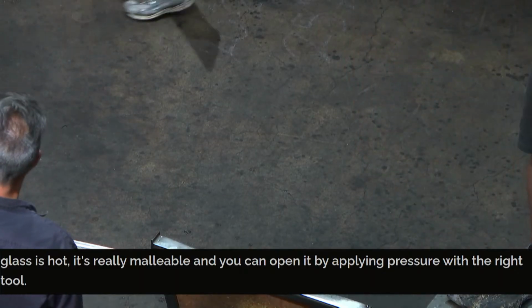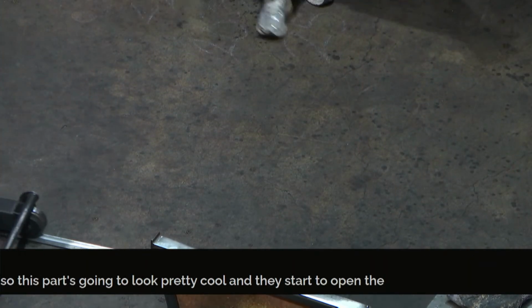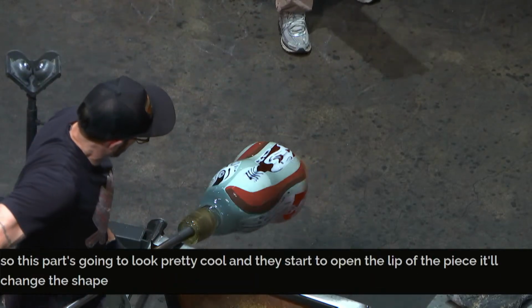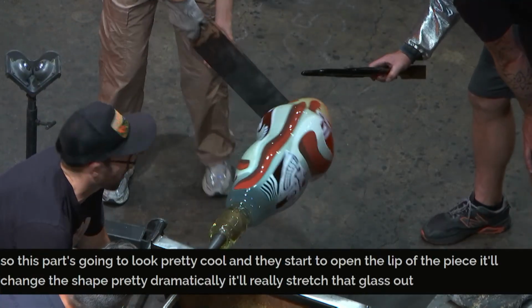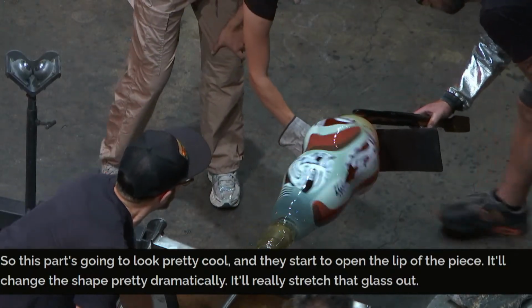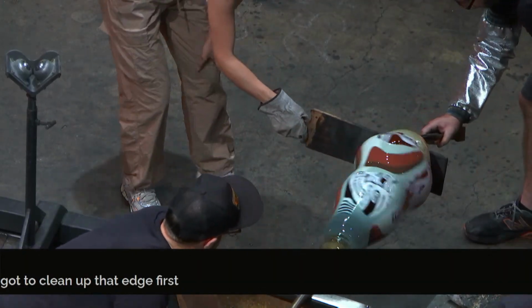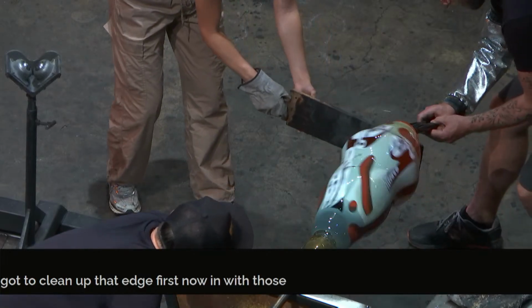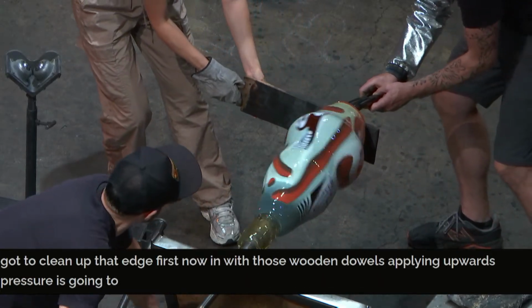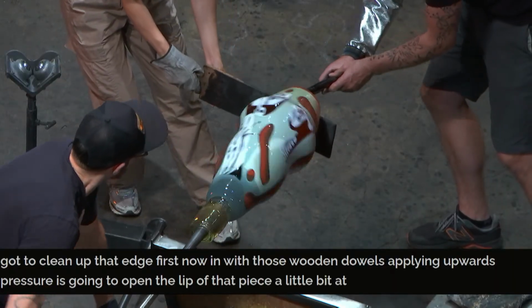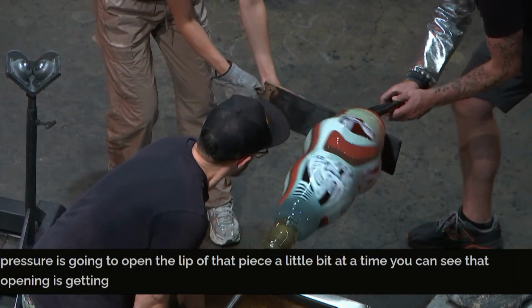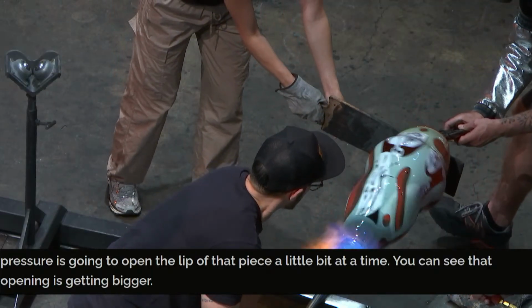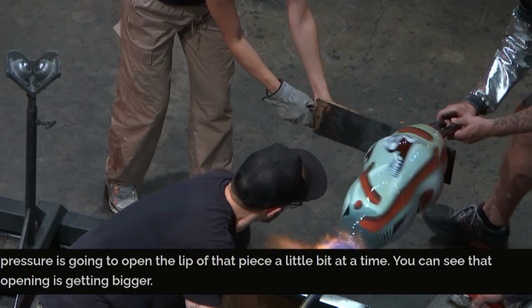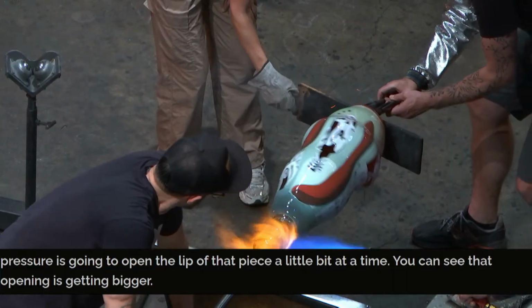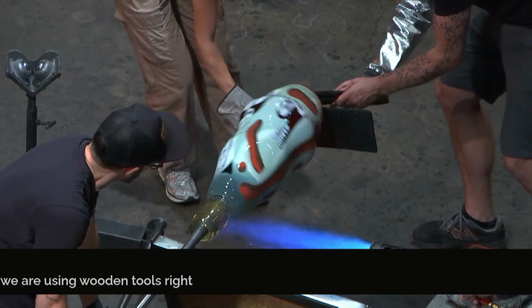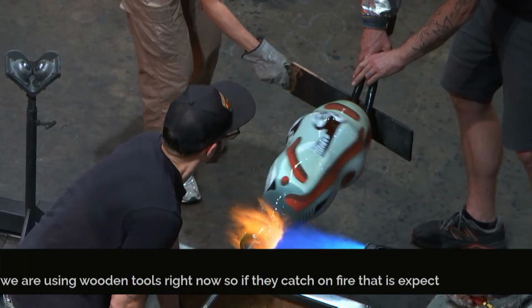So this part's going to look pretty cool when they start to open the lip of the piece. It'll change the shape pretty dramatically. It'll really stretch that glass out. Got to clean up that edge first. Now in with those wooden dowels, applying upwards pressure is going to open the lip of that piece a little bit at a time. You can see that opening is getting bigger. We are using wooden tools right now, so if they catch on fire, that is expected.